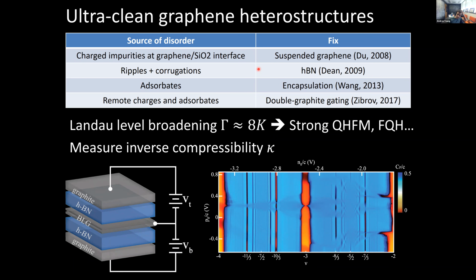So starting from the ideas of removing silicon substrates, then moving to single crystal two-dimensional materials as dielectrics. So in particular, all of our samples are made with hexagonal boron nitride dielectrics, which is a largely defect-free large gap insulator with the same basic structure as graphite. You need to have this on both sides.